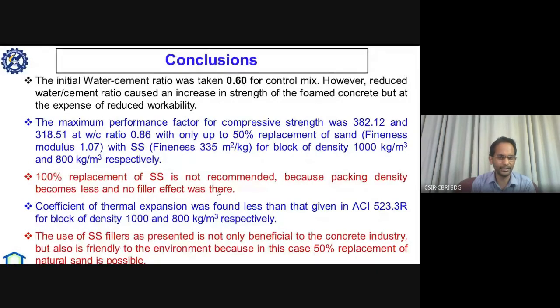And generally, it is not recommended to do 100% replacement with stone slurry powder, because the packing density will be quite less, and filler effect of course will not be there, because void ratio will be increased, and as you know, packing density is related with void ratio. More void ratio, less packing density. The coefficient of thermal expansion was found as per ACI 523.3R, for both kinds of series, that is S1 and S2. And thus the use of stone slurry powder as presented is not only beneficial to the concrete industry but also friendly to the environment, because in this case we can replace 50% of natural sand.